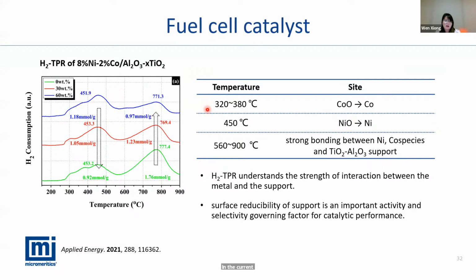The first peak, in the temperature range from 320 to 380, shows cobalt oxide reduced to cobalt at relatively low temperature. We can also see the peak at 450 degrees C is assigned to nickel oxide reduction to nickel. So in this case, it means different kinds of metal have different interactions with the support. When we do the TPR to check the strength of the interaction, we really want to see the relationship between the surface reducibility of the support and the activity or the selectivity of the sample.